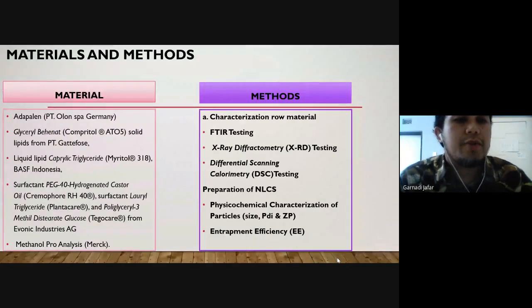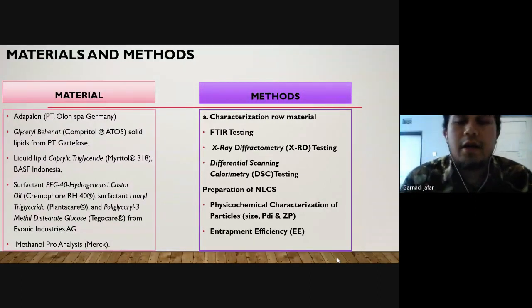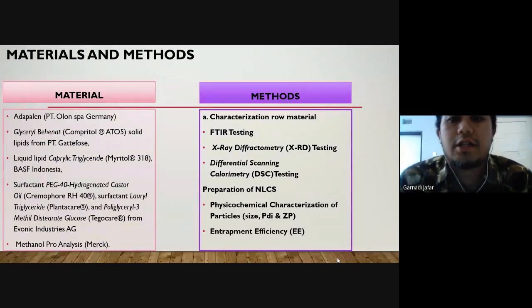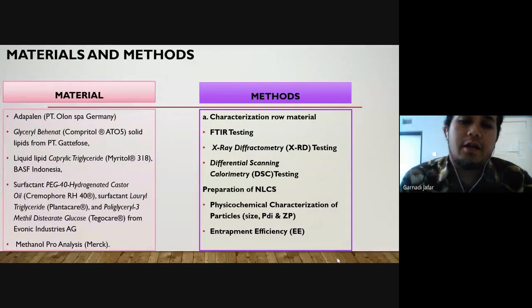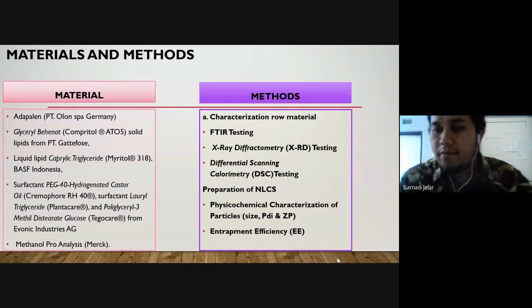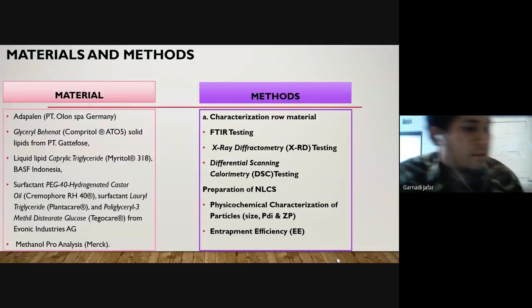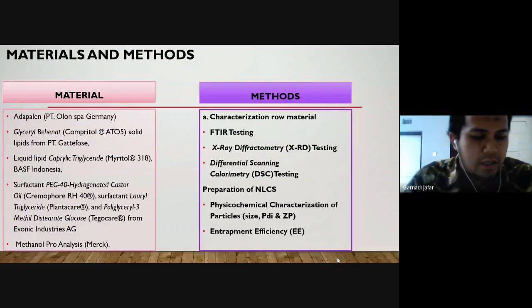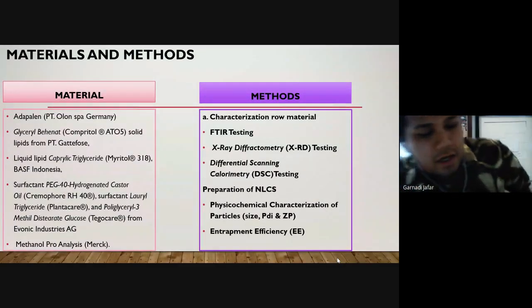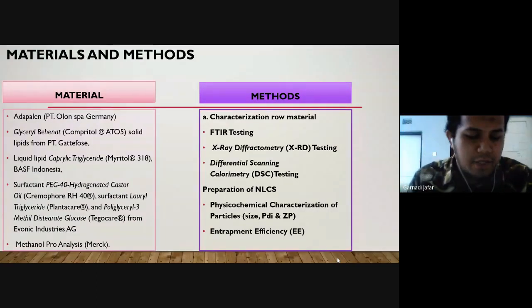Adapalene is from PT Olon Spa Germany, as we can see in the slide. And then the method. The first is characterization of raw material. Number one, FTIR testing. FTIR testing is intended to determine the compatibility of the materials used. This test is carried out by analyzing the active substance adapalene, Compritol ATO solid lipid, and the mixture of adapalene and solid lipid. The sample is crushed and placed in the sample container of the Agilent Cary FTIR spectrometer. And then X-ray diffraction.